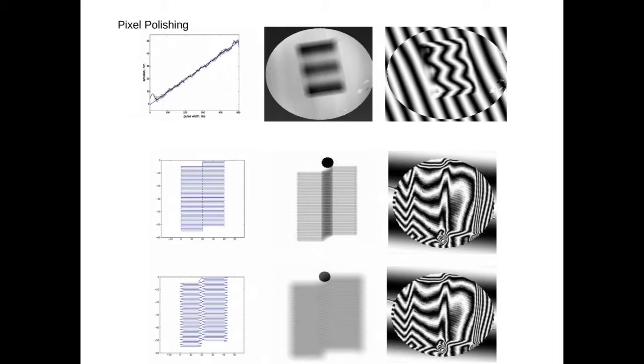A new HyDRA tool design has been developed which allows switching slurry flow without losing tool bias. Switching frequencies of up to 10 Hz and pulses as narrow as 10 microseconds can be achieved with this new tool. The ability to operate the HyDRA tool in a switched manner widens its overall performance and efficiency, adding new applications. This allows the use of polishing pulses that can be applied on a per pixel basis or in a continuous scan using pulse width modulation techniques. With this feature, dwell time can be controlled below the minimum attainable by a continuous action at the maximum CNC speed.